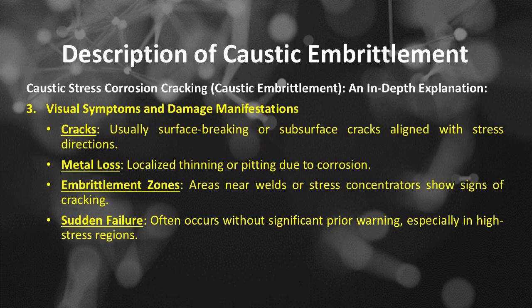Visual symptoms and damage manifestations of caustic embrittlement. It can be visualized as cracks, usually surface breaking or subsurface cracks aligned with stress directions. It can be visualized as metal loss, localized thinning or pitting due to corrosion. It shows embrittlement zones, areas near welds or stress concentrators show signs of cracking, and it can be sudden failure. Often occurs without significant prior warning, especially in high-stress regions.